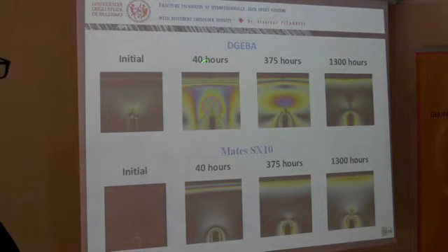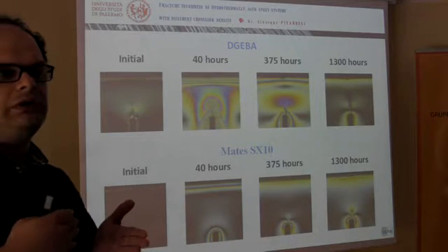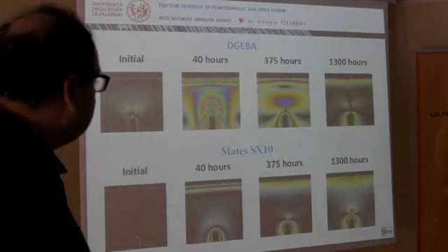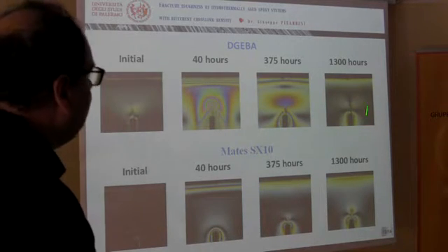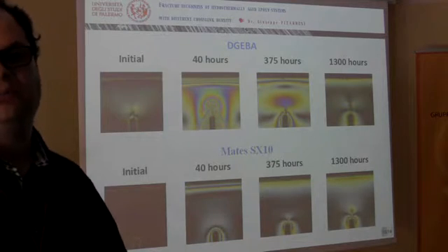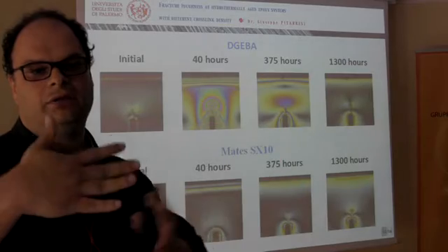This very severe stress field starts to relax again as the water progresses towards saturation. When saturation is reached, we regain a completely stress-free situation, because basically these stresses arise from the non-uniform swelling of the material.